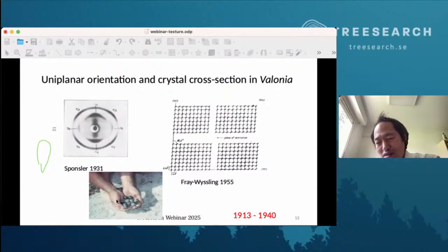cell wall, macroscopically, you have a preferred crystallographic orientation, not the chain axis orientation, but the plane of the cross section of the unit, the fiber, is oriented preferentially with respect to the membrane, and this will directly indicate a kind of shape of the building block in the cell wall without using the microscopy, without seeing each individual structure.